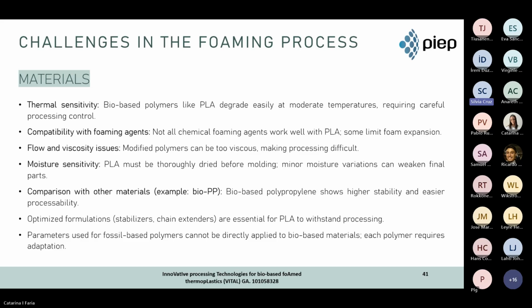Apart from PLA and looking at other bio-based materials, limited bio-based grades optimized for foam injection molding may lead to variations. So as circularity increases, variability increases as well. So it was possible to observe some fluctuations in melt flow index, inconsistency in the crystallinity, and mixed feedstock streams may reduce the final consistency of the injected parts. So it's harder to maintain stable microcell structures and quality. So tailored formulations and process parameter development could be needed for specific applications, and geometry adjustments to compensate, for instance, impact deformation or aesthetic defects, may also be considered.